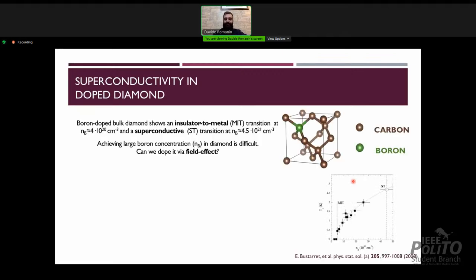Now, as a first example, I would like to discuss diamond. Why diamond? Because in 2004, it was shown that if we dope bulk diamond with boron, then we can achieve first an insulator to metal phase transition, and then a superconductive phase transition with a critical temperature of around 4 Kelvin. However, even if theoretical predictions suggest that this critical temperature can be raised by increasing the amount of boron inside diamond, there is a solubility limit due to the amount of boron that we can incorporate chemically into the closely packed structure of diamond. Therefore, we ask ourselves, can we dope it via field effect and still achieve a superconductive phase transition?